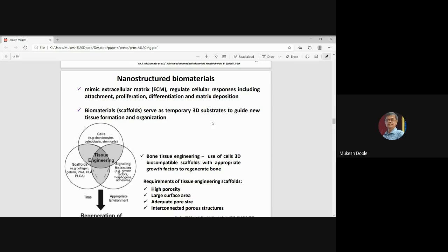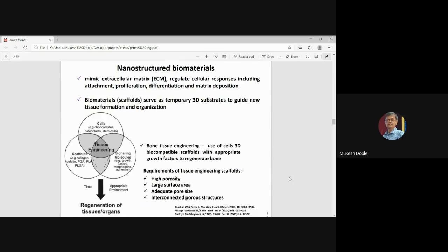In tissue engineering, we need high porosity. So nanostructured material can help in getting high porosity. That means it can have high surface area per gram of material. And we can also design adequate pore size. So you don't have to go very nano in size, like 2-digit nanometer scale, but you can think of 3-digit nano, like 400, even 500 nanometer, so that we can help in cell adhesion. Because when you talk about biomaterial, especially for tissue engineering, the cells, the scaffold, the signaling molecules, all we need to consider if it is going to have regeneration properties actually.